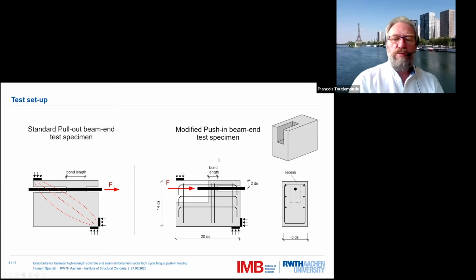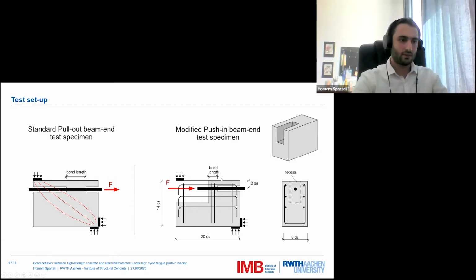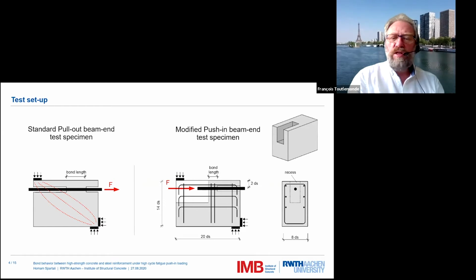And so do you consider it provides some confinement that can affect your results? Of course, the confinement level is important, and without these stirrups, we could expect earlier failure in the bond, or failure with lower loading levels in the monotonic case. And so that's my comment and question. Do you consider having variation in the cover depth to bar diameter ratio so that you can finally obtain a pure bond failure mode and not a mix?